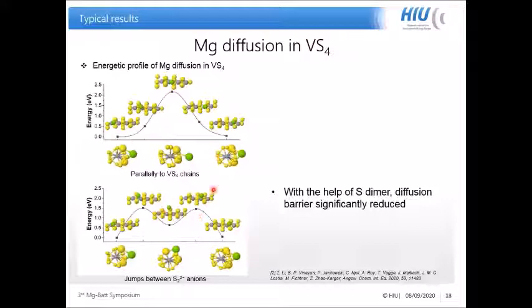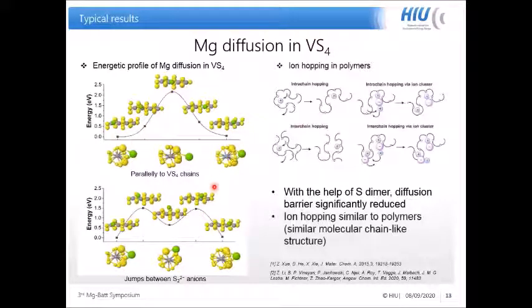This result is quite interesting, and it reminds us of ion hopping in polymers. If we look at the structure, VS4 is also kind of like a polymer structure. It has a molecular chain structure, and that's why it might have the same hopping mechanism as in the polymer cases. But in the case of polymers, because they are even more flexible than the VS4 structure, this also allows even interchain hopping, or even ion cluster hopping together with some anions or clusters. So this is quite interesting.